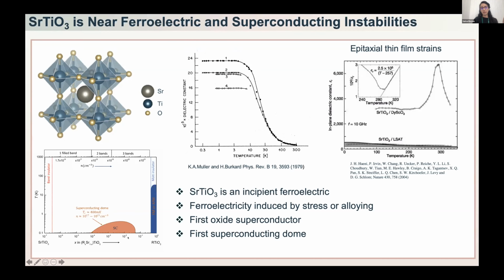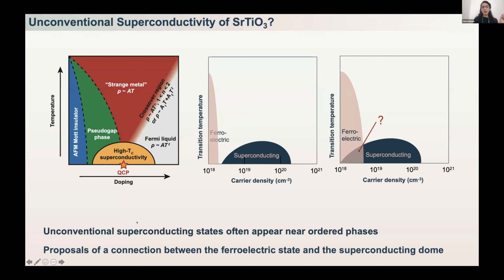As you can see here, the peak of superconductivity happens at around 350 millikelvin, at a carrier density of around 10 to 20 per centimeter cubed. And this was, in fact, the first oxide superconductor that was discovered, and the first superconducting dome that was discovered. But now we know that this superconductivity happens next to ferroelectricity in this structure.